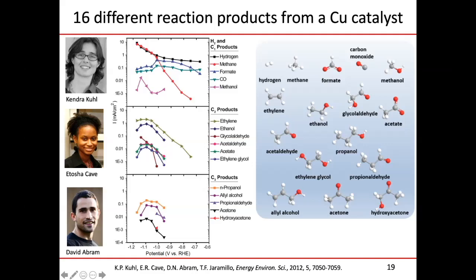Some of that initial work from Kendra, Etosha, and David, you can see that they were feeding CO2 here. It's a simple copper catalyst at standard temperature and pressure, 0.1 molar potassium bicarbonate. And amazingly, they detected 16 different products of reaction. We had really engineered our devices, our reactors, to be sensitive enough to identify and quantify the products of reaction. The good news is that copper can make all these really interesting products, but there are some challenges. First of all, it's a big mix, and I mentioned separations is a challenge. So it's totally not a selective catalyst. That's a problem for a commercial technology.